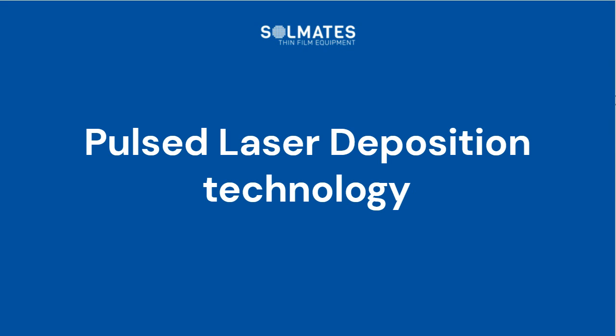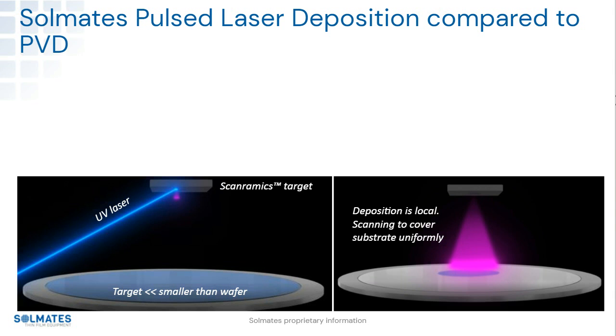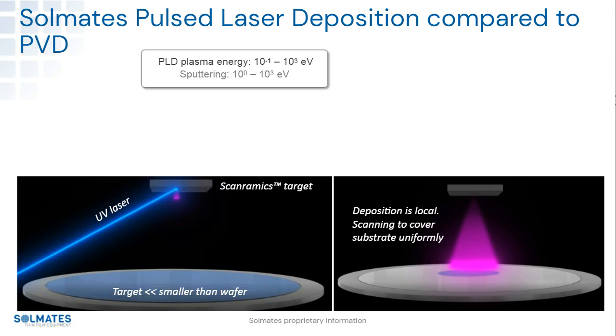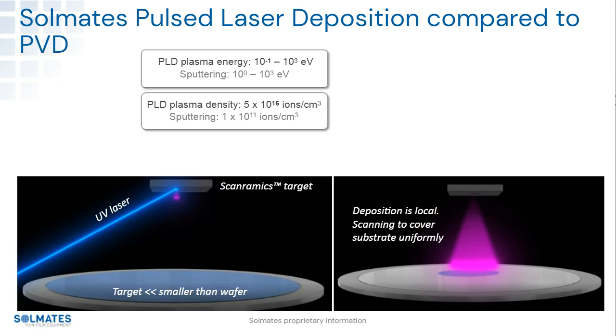So this was a less than 1 minute introduction into the PLD basics. There's much more to it. Maybe, Arjen, can you summarize for us? No, I think in the beginning I said why we are on this mission is because we believe and see that this technology is different. And if you look at the pictures, the stills from the video, but also at the physics behind it, you can see that the main difference with sputtering, which is where we are compared to the most, is the density of species in the plasma.